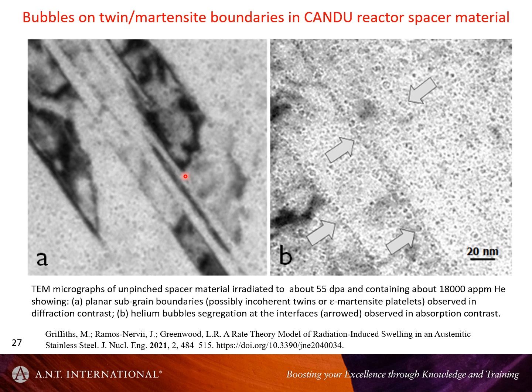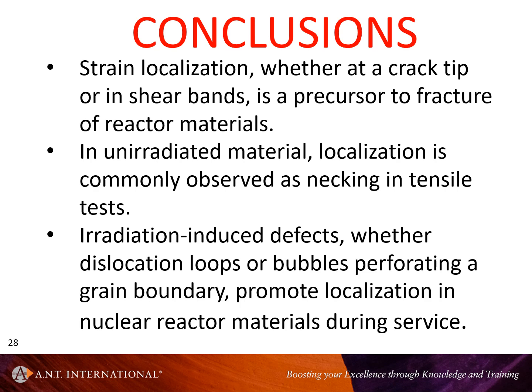So if you're seeing intergranular failure because of the helium segregation, why not get failure of what are likely incoherent twins? I mean, the fact that they're not very straight, you can see here that they have different widths, that these are incoherent to a large extent. So, I mean, it makes perfect sense that that is one of the explanations.